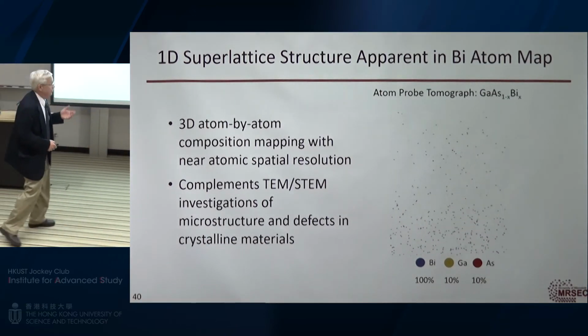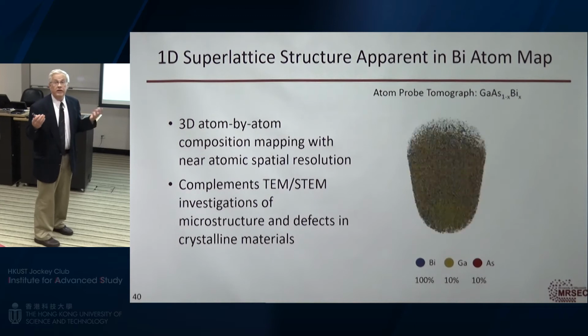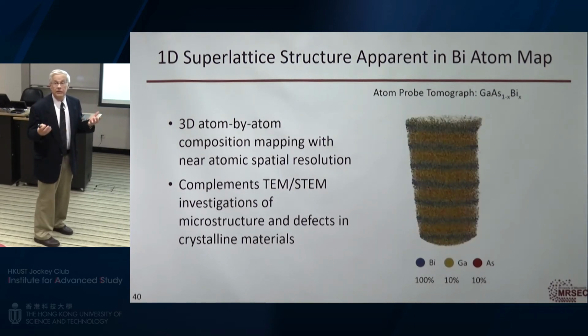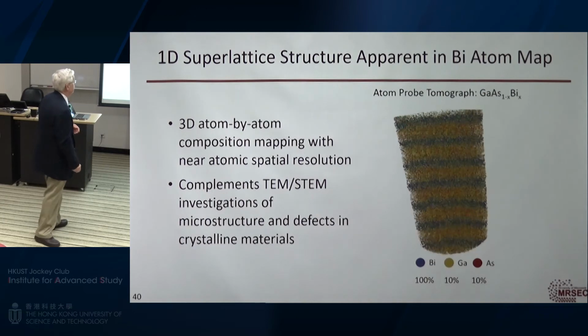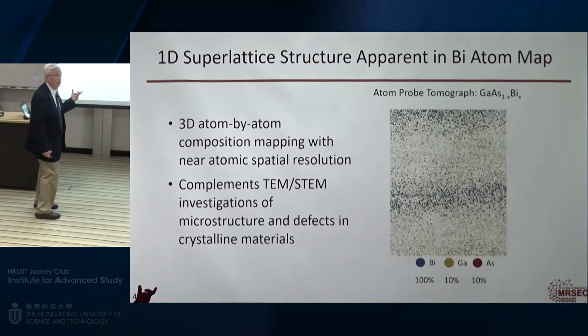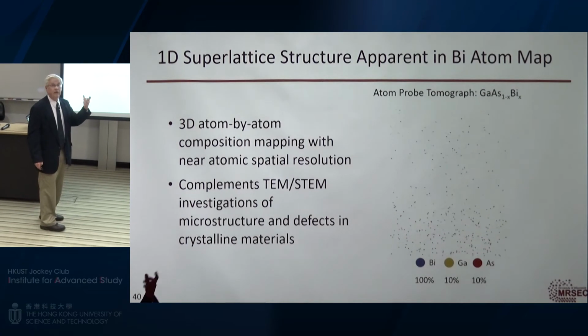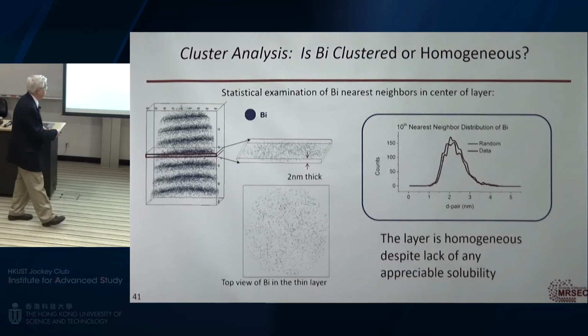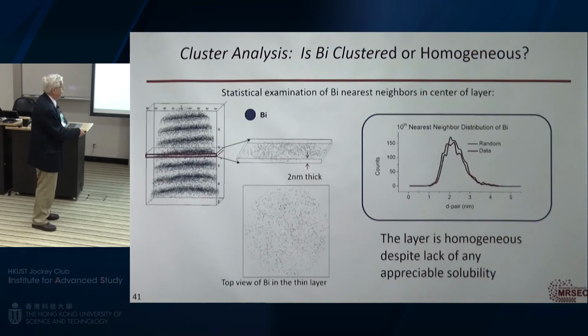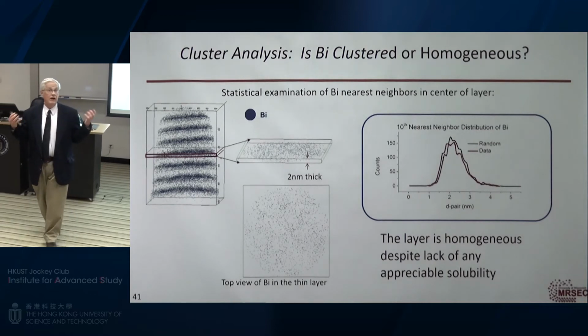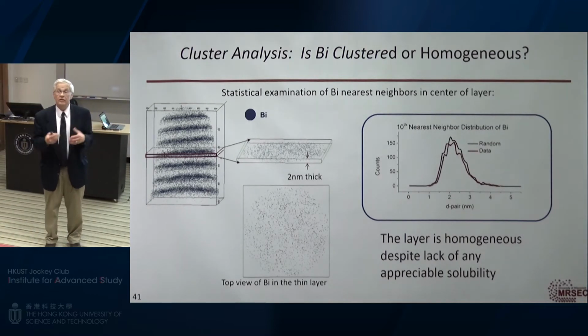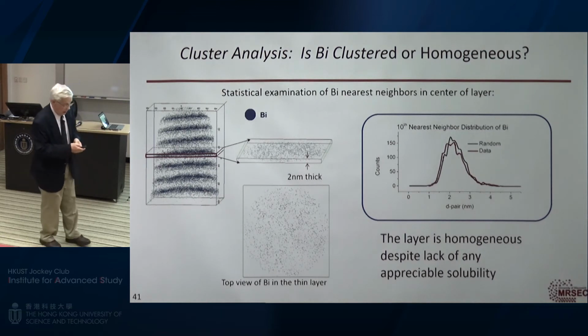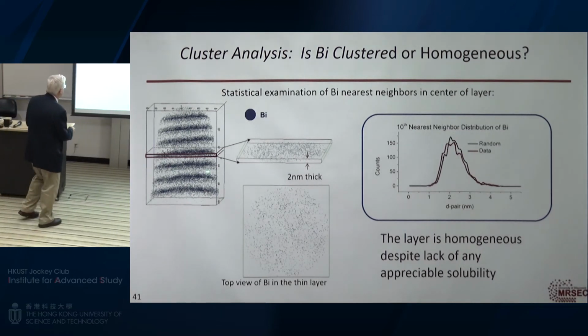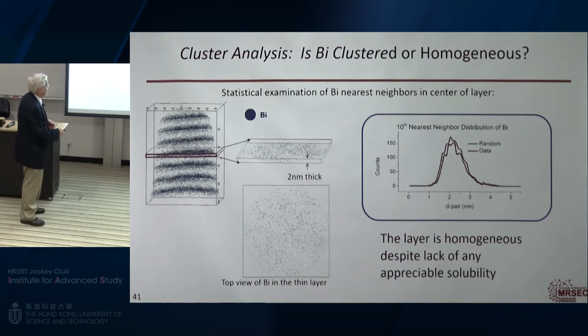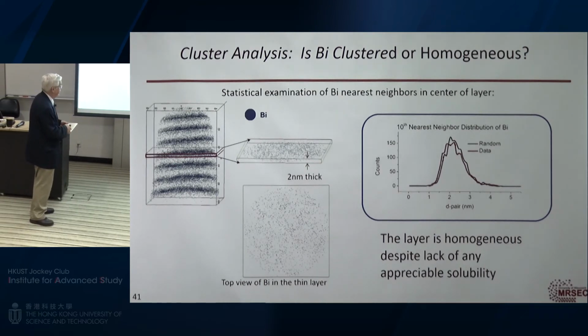And we can use this to analyze what is happening inside the material. If I have a material that wants to phase separate, one of the things I want to know is, has that started? Are there more bismuths near other bismuths than not? And we can analyze that, and we find out that the layer is homogeneous, meaning that even though it doesn't have any solubility, I put lots of bismuth in it, and it's a random alloy. So that is a metastable material. It doesn't want to have bismuth in it. It's a homogeneous alloy in this region, and we have analyzed that.